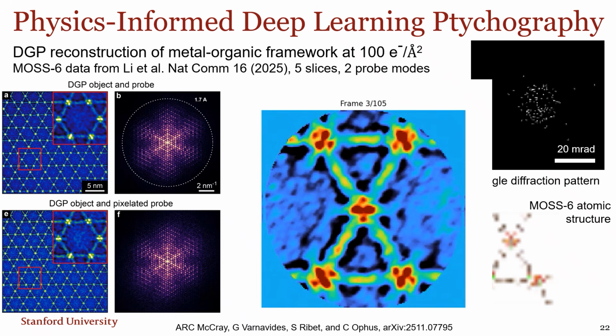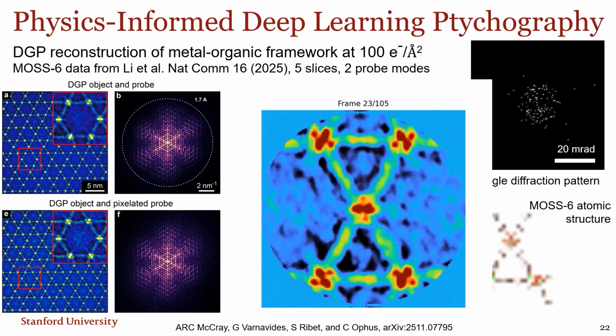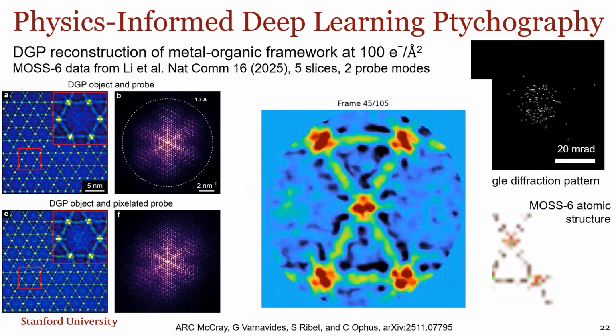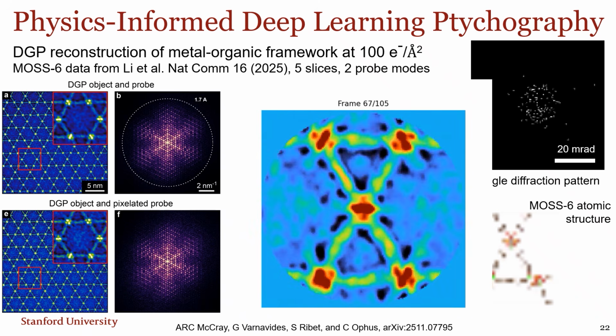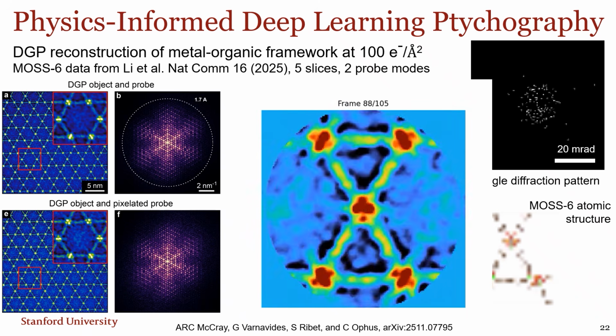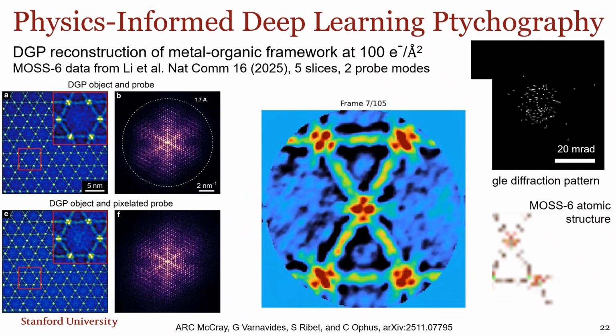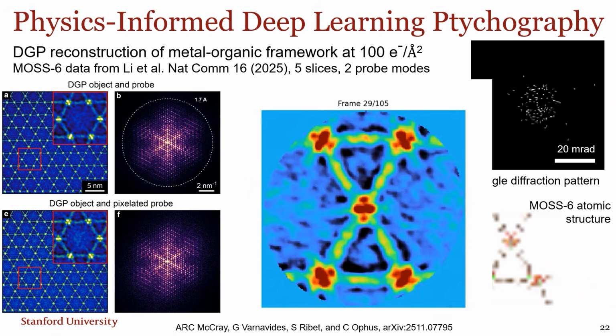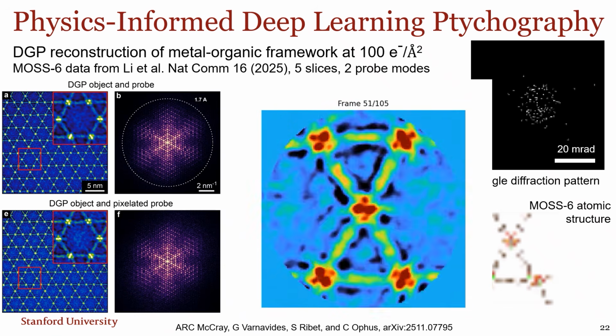And so I just want to zoom in and look at each one of the structural units here and loop through them. You can actually see the two bright dots of the two zirconium atoms in projection next to the two dim dots of single zirconium atoms. And in between, it's empty space. These metal organic frameworks are mostly vacuum. And this is actually one of the reasons they're so beam sensitive here.